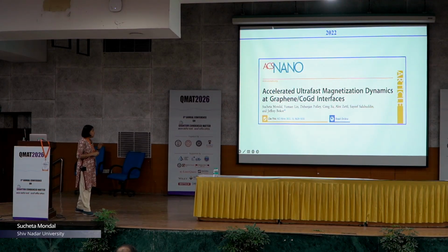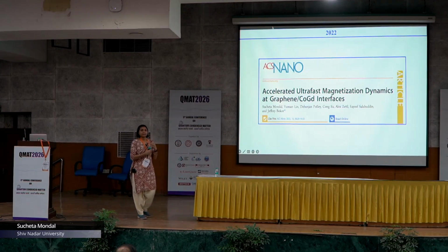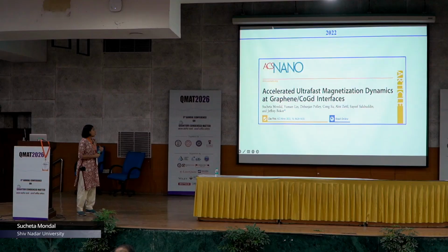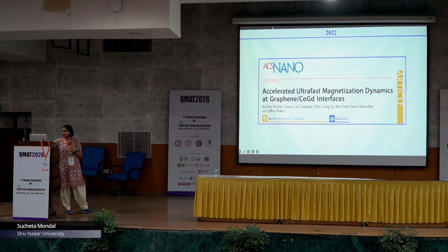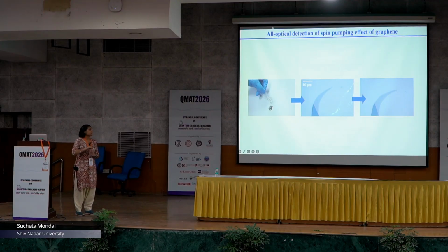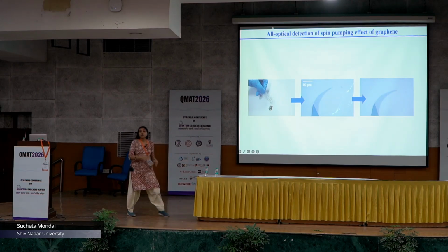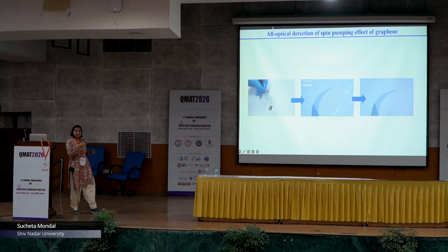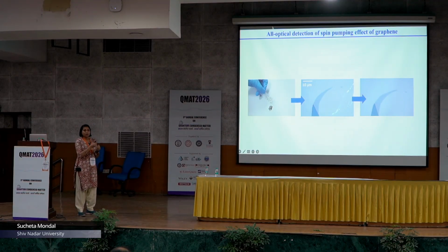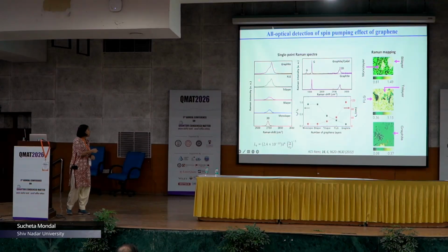The last part of the talk which I would like to touch on is when we performed optical experiments on the graphene and cobalt-gadolinium system, and what we observed. We tried the regular exfoliation method, which is cheap and effective. Many studies have also been done in Professor Muduli's group and Professor Baumann's group before. This comes after that, and we tried to exfoliate different layers of graphene. We kept the ferrimagnetic layer thickness constant and varied the graphene layer thickness, and fortunately we could achieve from monolayer to bilayer to trilayer to few-layer and graphite.